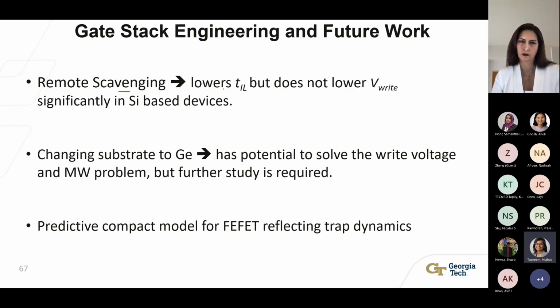So we learned that remote scavenging can lower the interfacial layer thickness, but cannot lower the write voltage significantly in silicon-based devices. So we can move on to silicon germanium-based channels. Now, changing substrate to germanium has the potential to solve the write voltage and memory window problem. However, there is still a long way to go and further study is required in this regard. Finally, the extensive data that was collected in this thesis can be aggregated to develop a predictive compact model for FeFETs that can reflect the trapping dynamics in these devices.